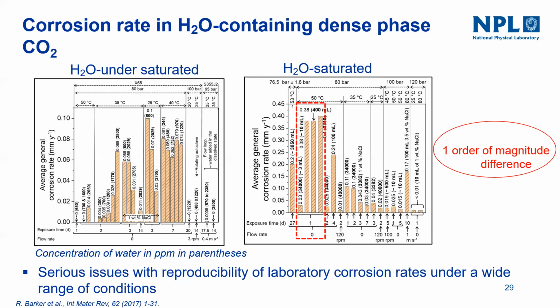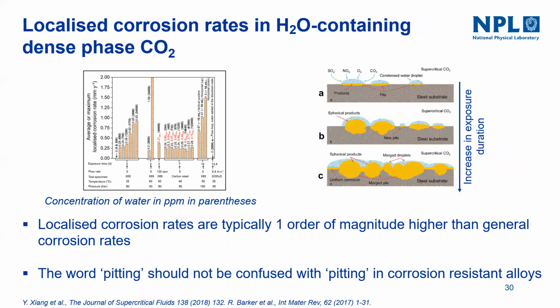It's really concerning. Similarly for localized corrosion rates, typically one order of magnitude difference has been reported. And the second thing is that people normally use the word pitting for these cases in low carbon steels. It should not be confused with pitting in corrosion resistant alloys. What it exactly means is they have localized corrosion, with a much deeper attack compared to other regions. So it's better to call them localized corrosion regions.